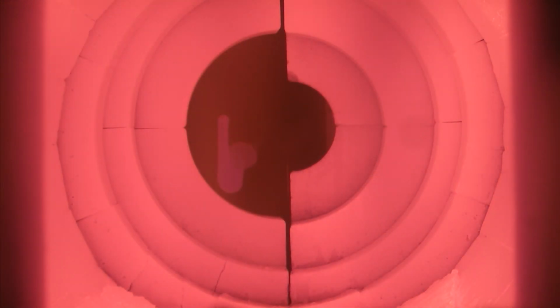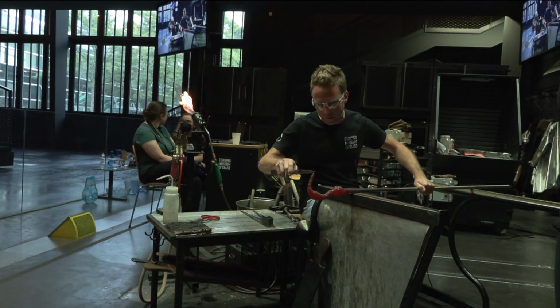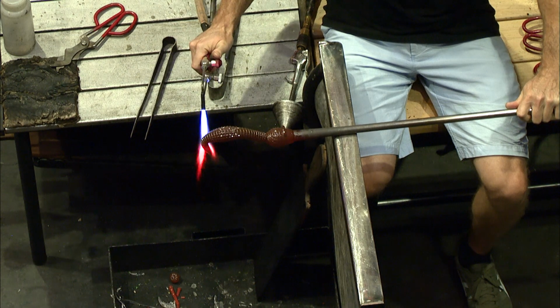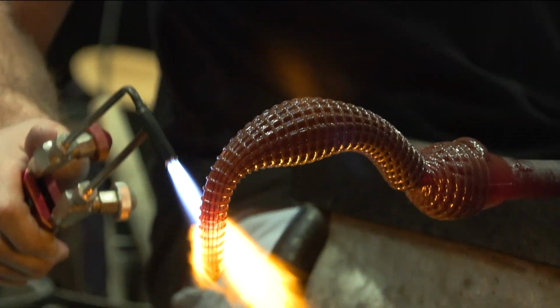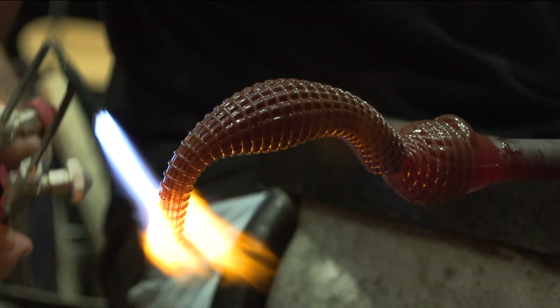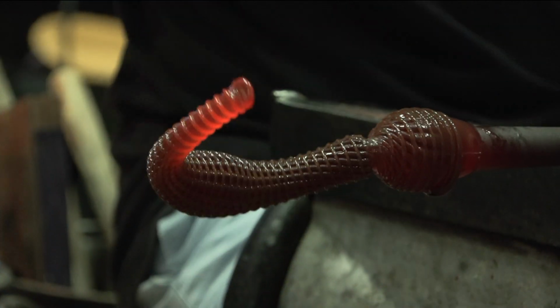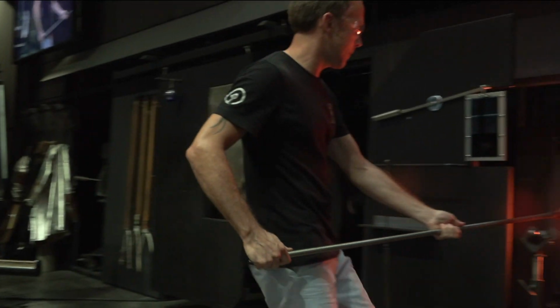And another thing you might notice as he's building this whole thing together as well is that traditional styles are generally rolling the pipe back and forth and keeping things centered the whole time. But as soon as you start creating things off-center, it changes a little bit in the way that you approach that glass. So as he was holding on to the tail bit, he was letting the belly kind of sag. So we're using gravity. We can use gravity to elongate or compress forms, or just kind of use them to create lovely curves. But you have to set up the temperatures to get just the right curve as well. So back and forth quite often you'll see into that reheating chamber.